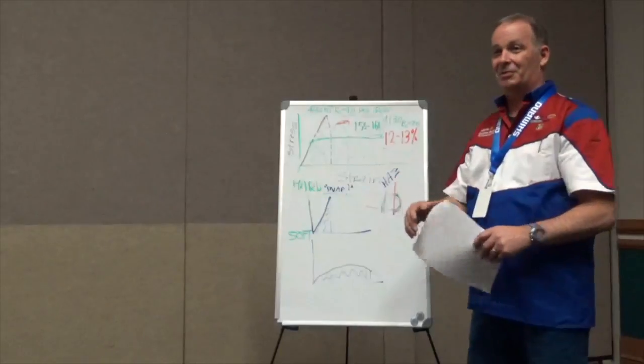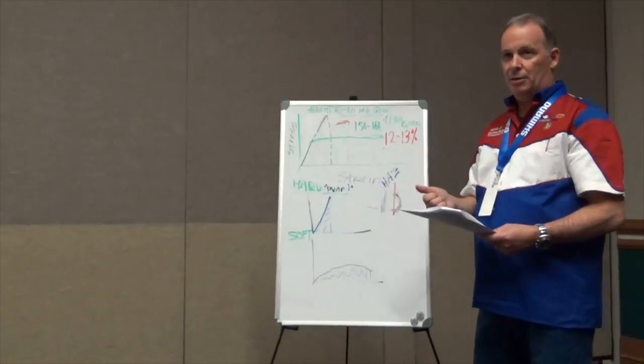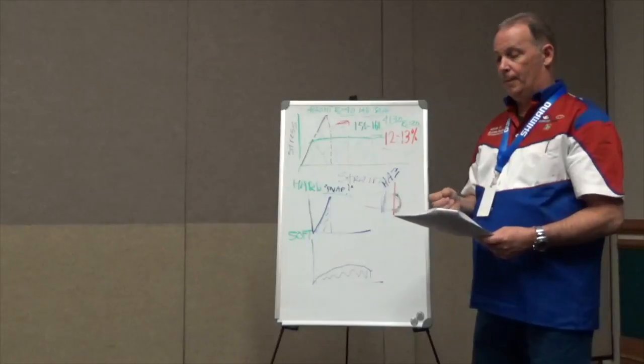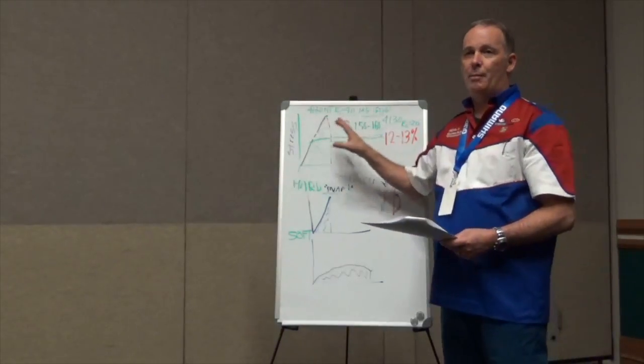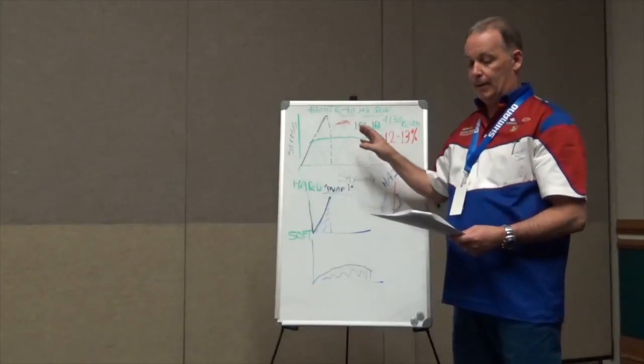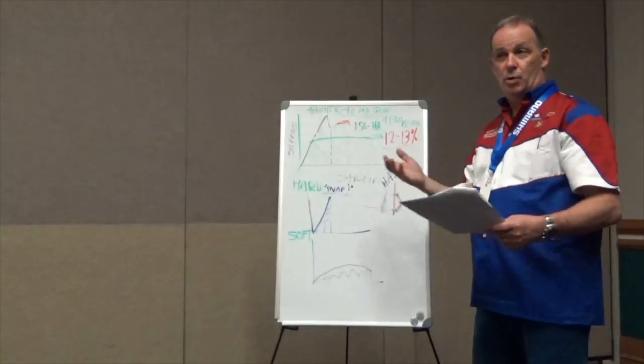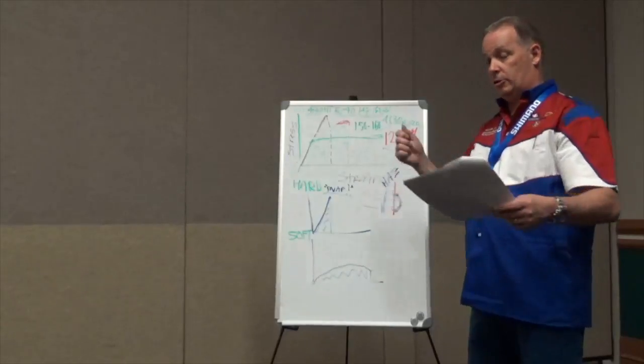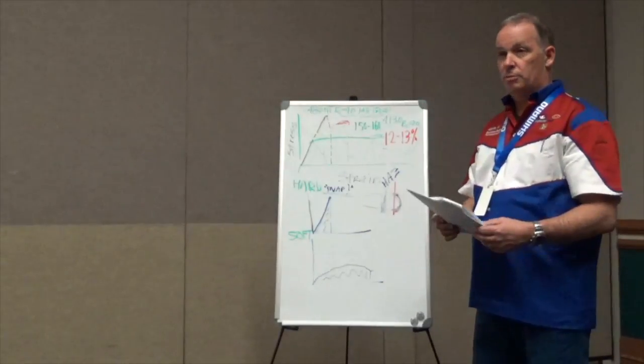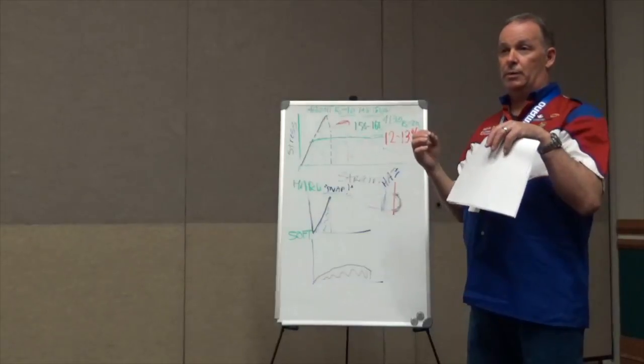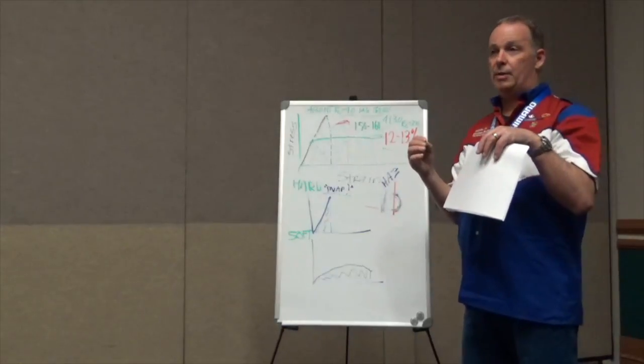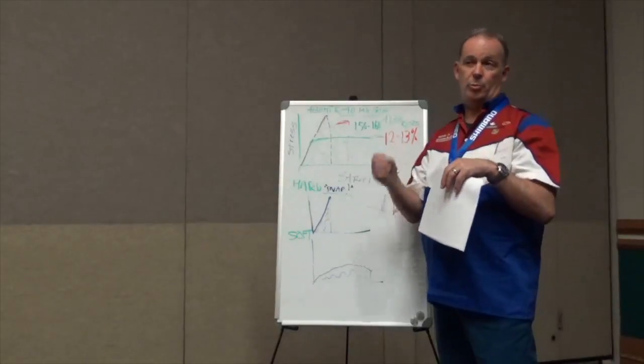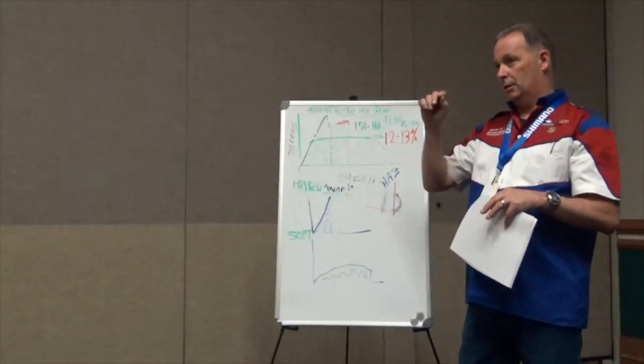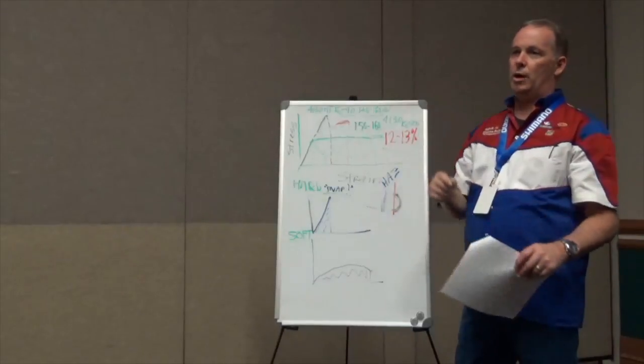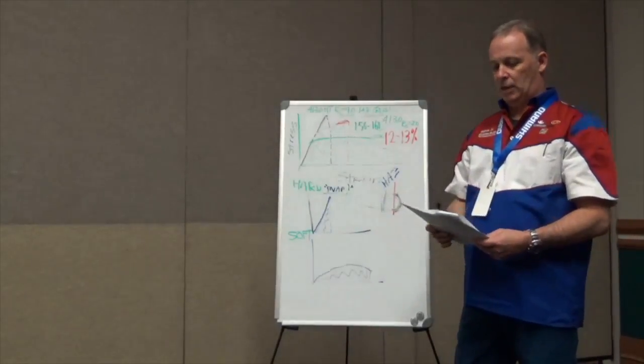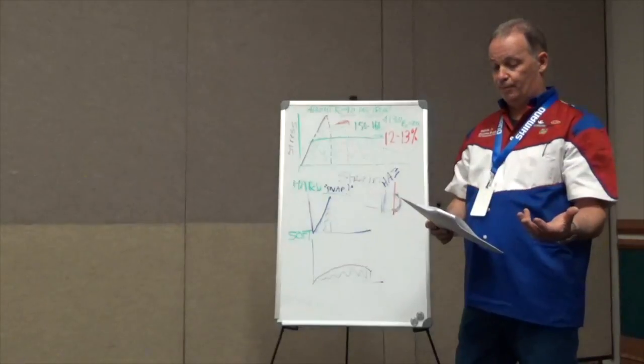Here's the conclusion, last page. Tensile and hardness really do matter. And it's not just one or the other, it's really the balance of both of those. Not enough, a frame prematurely fails, it acts like taffy, it just stretches and bends. Too much, and it literally separates at the joint. And if you've been around very many frames where guys went to really thin, super hard tubes and you watch them TIG them, you'll have seen some that had cracks right around the edges of the welds. Just too hard.